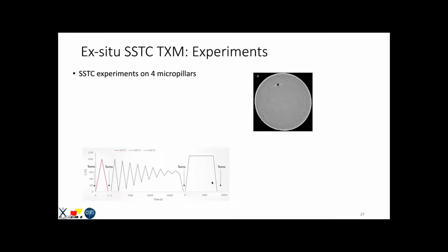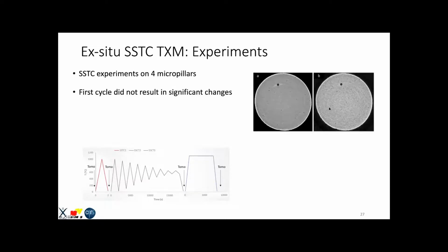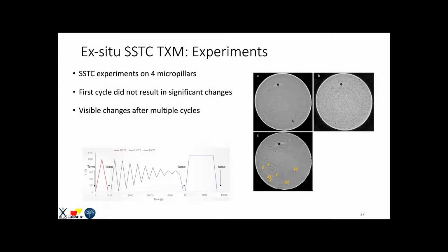So this is the initial state. You can see a bunch of precipitates over here. This is the state after the first cycle. So this one, a single cycle, did not result in significant changes. We didn't see anything that was different from this state. After this cycling, we saw some visible changes. So there were new precipitates that popped up. Some of them grew, some of them shrunk, some of them coalesced. Probably that was what we saw as growing.